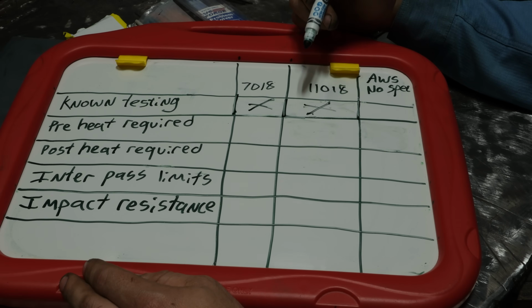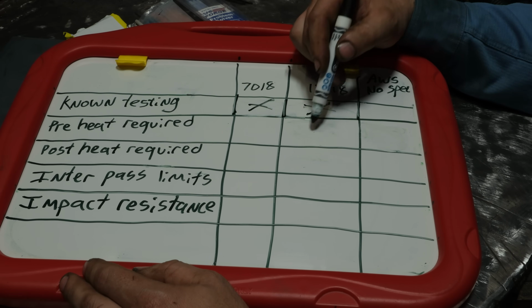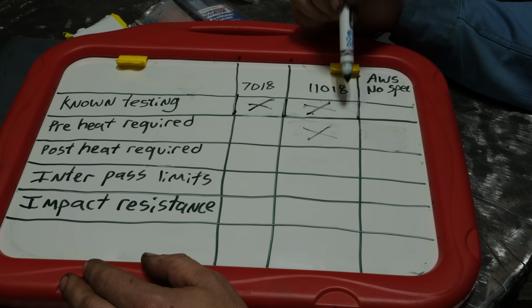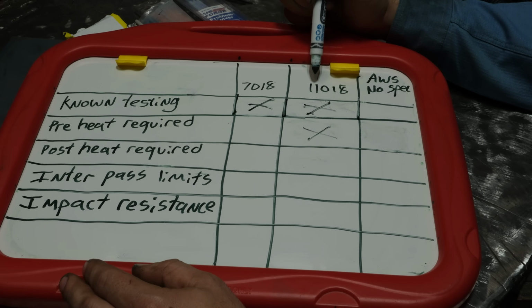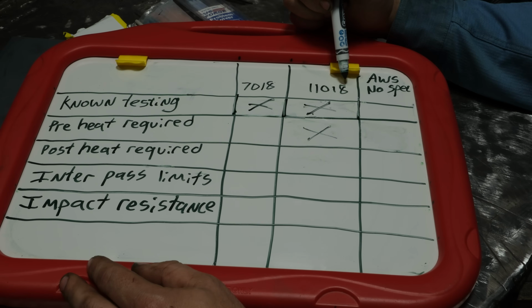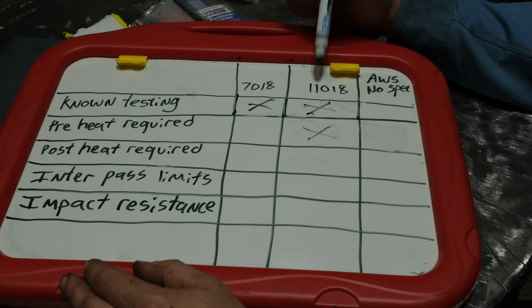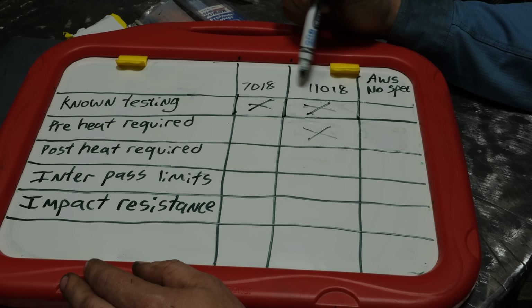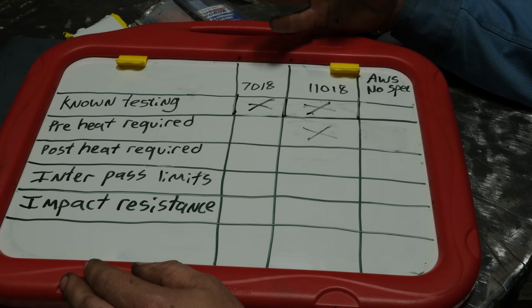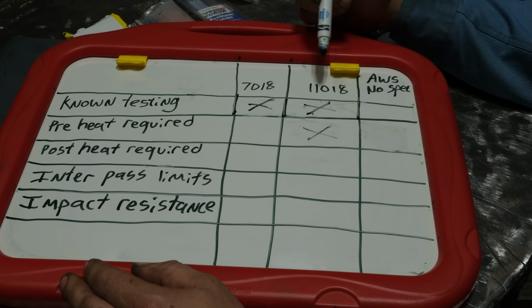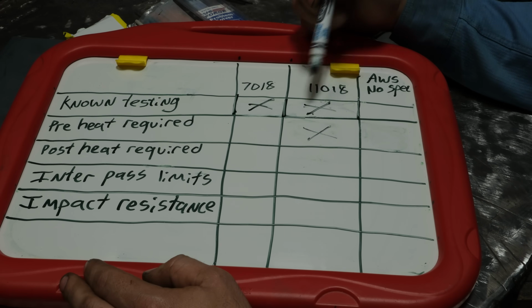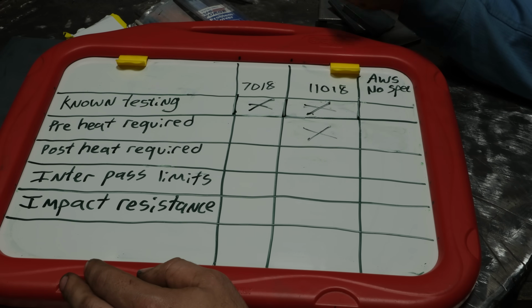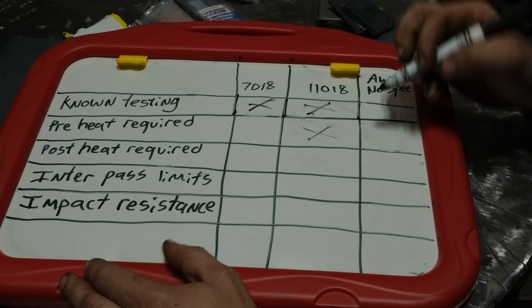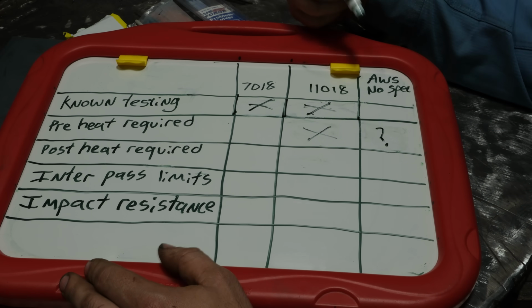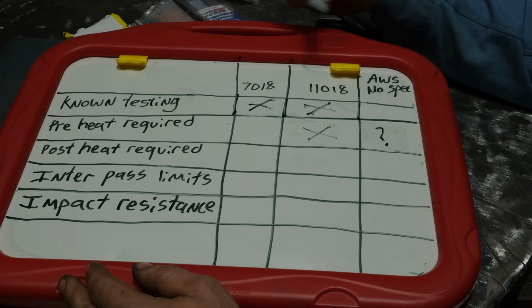11018, if you were to weld that on high strength steel, you would need a preheat. However, one of the issues here is that if you were to weld mild steel with 11018 and you didn't preheat the mild steel, it's possible that the weld may cool too fast and then crack. And we may see that today when I weld mild steel with this product, is that the weld may not even make it to cool down before it fails. I don't know for sure, but we're going to find out on that. So that is a detriment. So preheat is a concern. Now, non-AWS spec, who the hell knows? It might not. Again, we have variables that we don't know about.